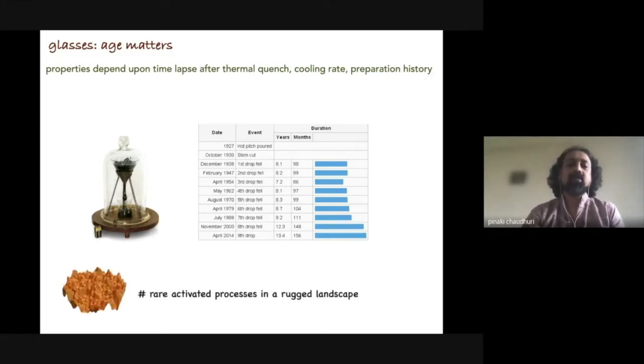So what is essentially happening is that the system, as it proceeds in this landscape to lower and lower temperatures, can get locked into one very deep minimum, and the ambient thermal fluctuations are not sufficient to kick it out. It takes a rare event to kick the system out of the local minimum and go to the next minimum, and so on. So it also gives us some information about how rugged the local landscape is in this high n-dimensional space.